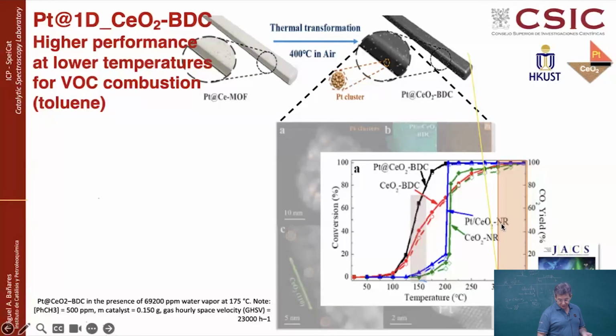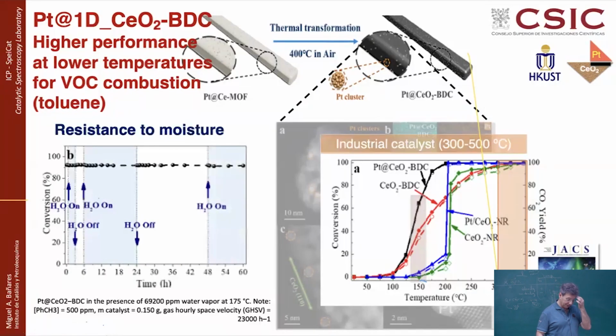You can synthesize conventional nanorods that do not come from metal organic frameworks, with or without platinum, and their performance is not that good, particularly below 200. So this system is particularly efficient, and we want to know why. Of course, because of the very close interaction between platinum and cerium, and also keep in perspective that the industrial catalysts are good above 300 degrees, and here we're getting very nice results at 200 and above, which is very attractive. And if you look, for instance, at the system working at 150, you can see that it's a dramatic difference already, like 60 against something like 40% conversion of toluene into carbon dioxide.